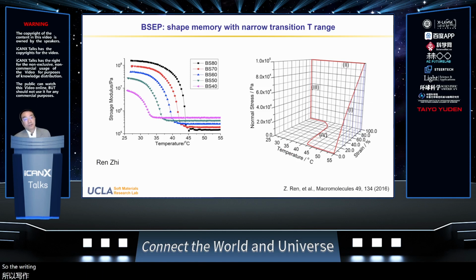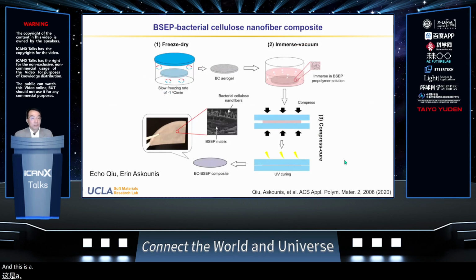So the right chart shows that this polymer actually shows excellent shape memory behavior, with an excellent shape fixation rate and shape recovery rate. And with this BSEP polymer, at the rubbery state, the maximum strain we can produce from this polymer is about 60%. And the modulus, to further increase the stiffness of this polymer.